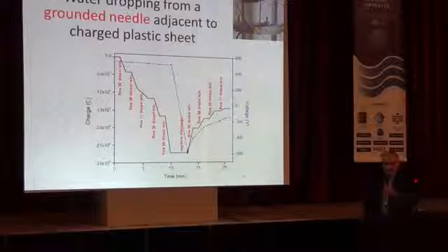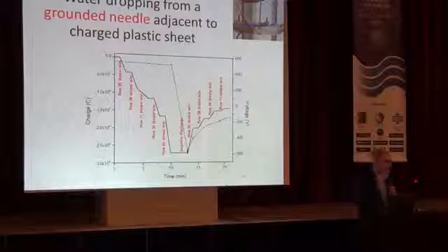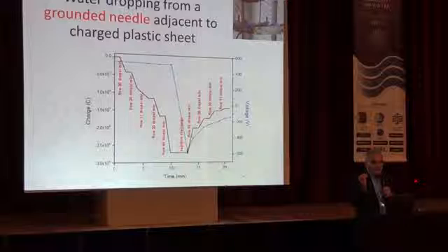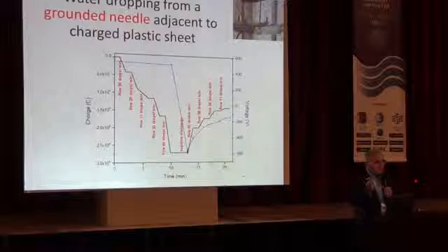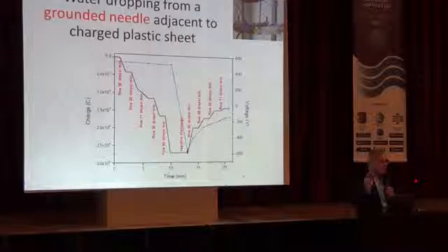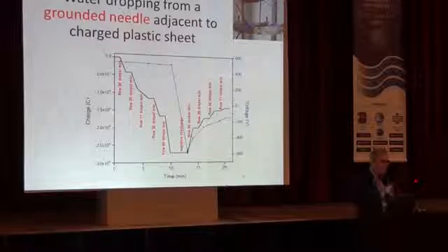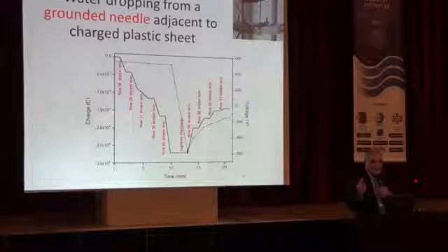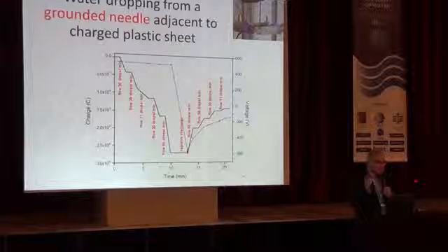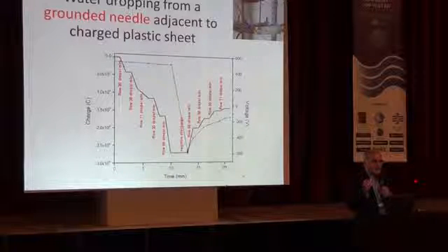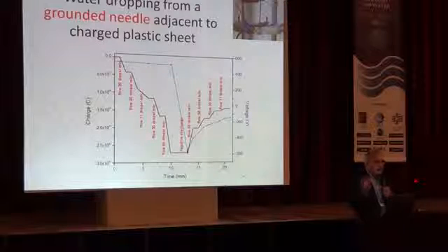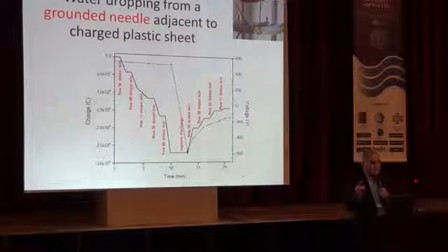But this is very important because it shows that whenever you have water, especially drops of water or aerosol, and you have insulators around, and insulators have charge, and any handling of the plastic and many ceramics will actually impart charge to them, then water in its presence will be charged.